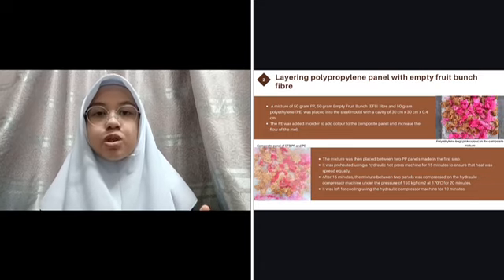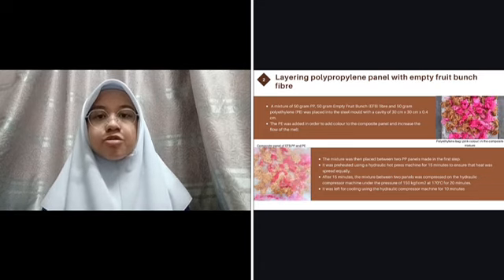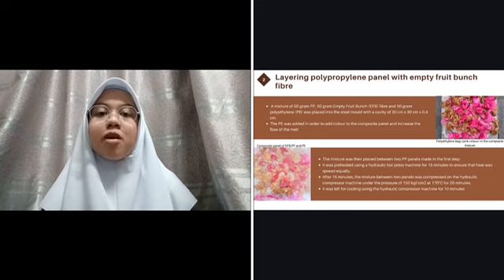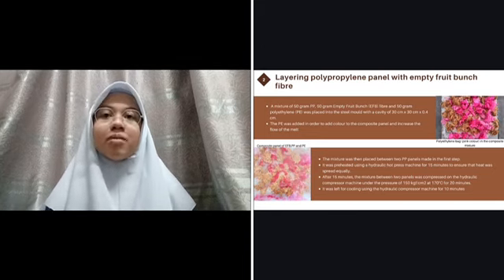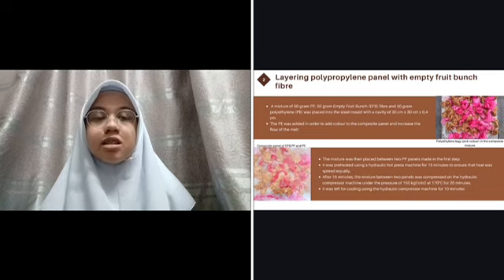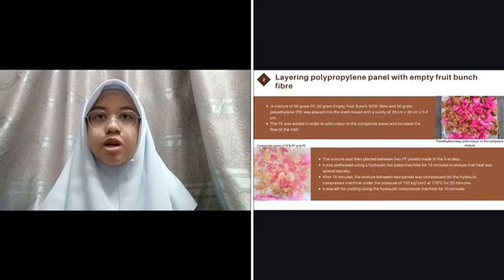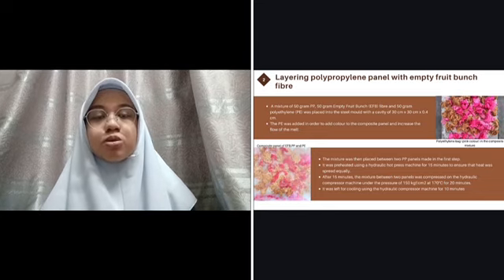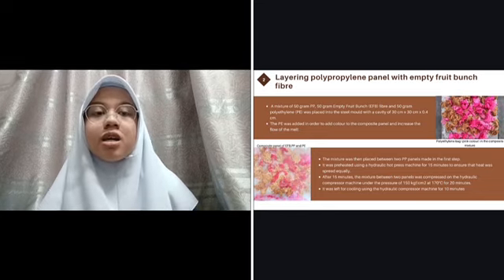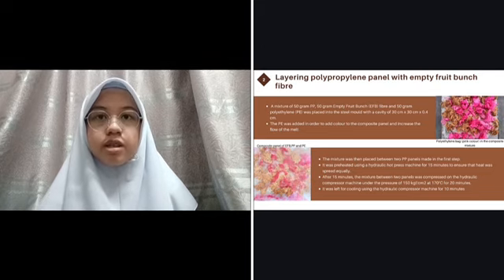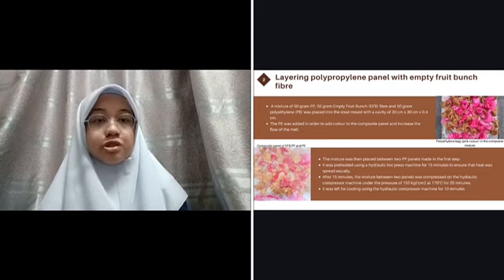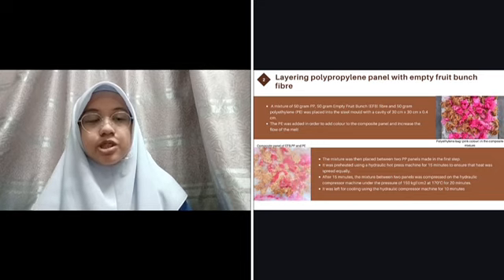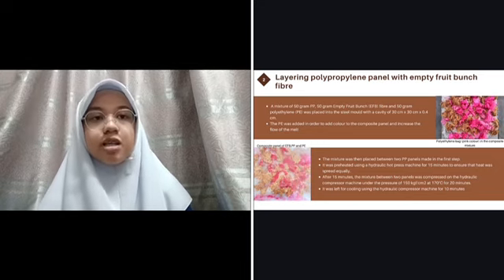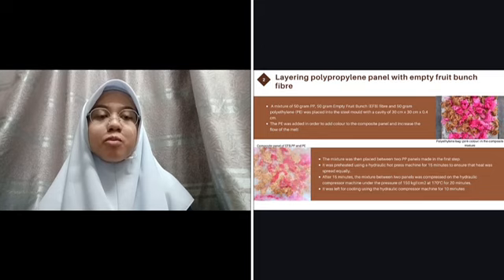For this step, we use 50 grams of empty fruit bunch fiber, 50 grams of polypropylene pellet, and 50 grams of polyethylene in the form of plastic bags. As seen in the picture, the pink color is the polyethylene. We add the polyethylene to add coloring to the composite and to increase the flow of the melt.